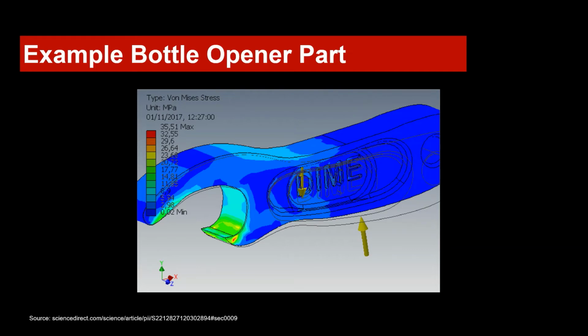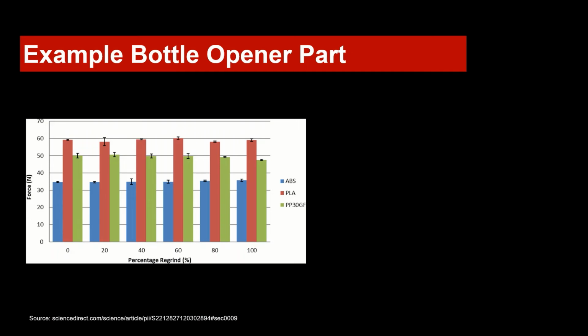Okay, let's have a look at some of the results. So here are now the three materials. In blue the ABS, in red the PLA, and in green the polypropylene with 30% glass fiber. And we have here the percent of regrind starting from 0 up to 100%, and then the force which is needed to break the part.